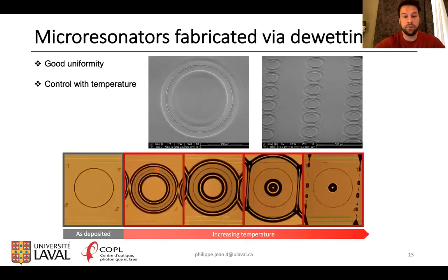So next, if we move to microresonators fabricated by dewetting, we can again see that the uniformity is pretty good over a large area with very uniform dewetted microresonators. We can also see that we can control the dewetting by changing the temperature. But here, if you have too low a temperature, you'll end up with incomplete dewetting. Whereas if you go too high, you might end up with a loss of material. So there's a trade-off here.